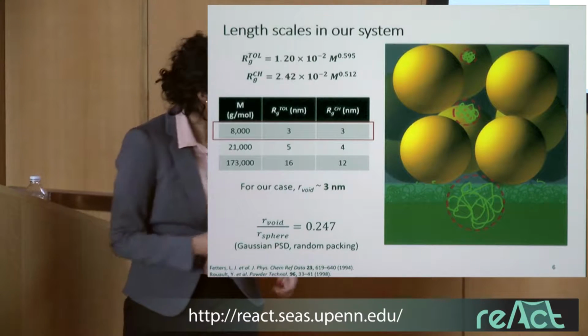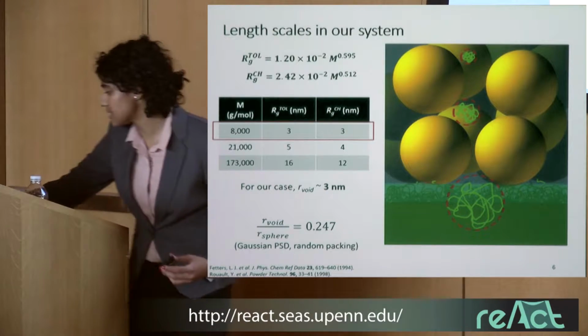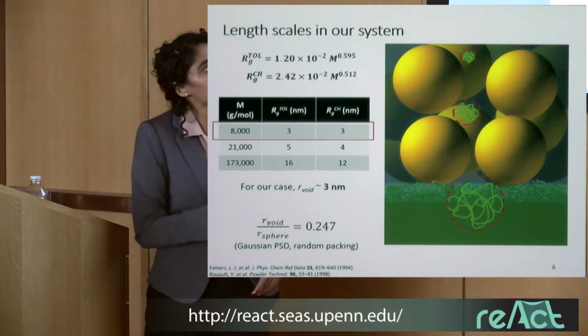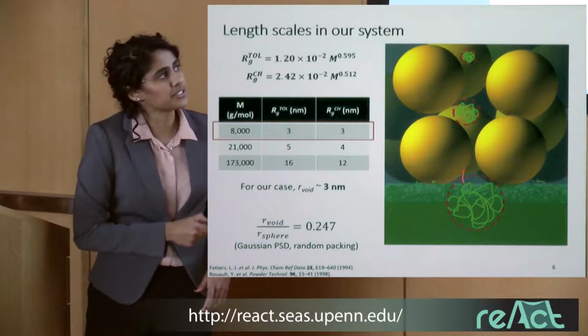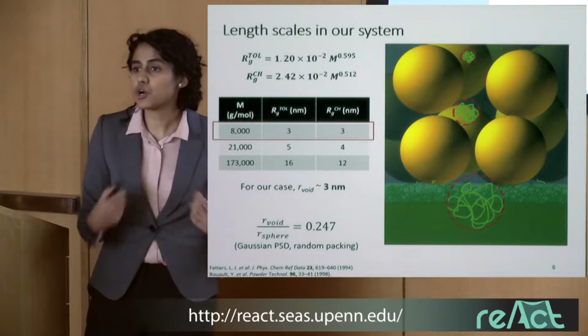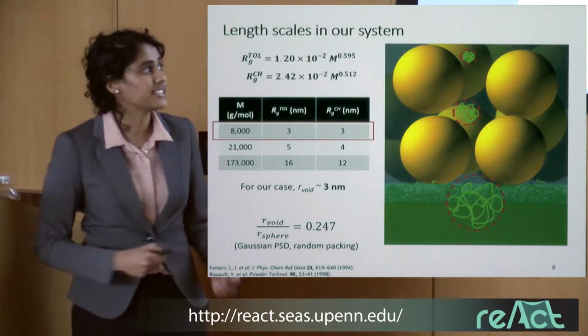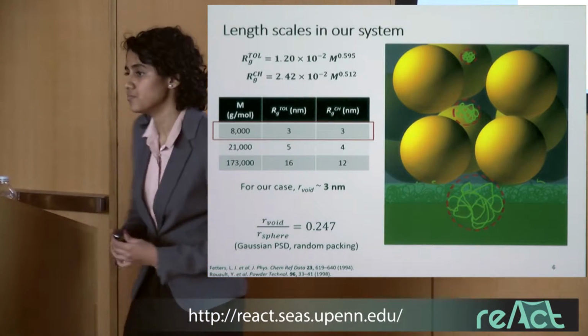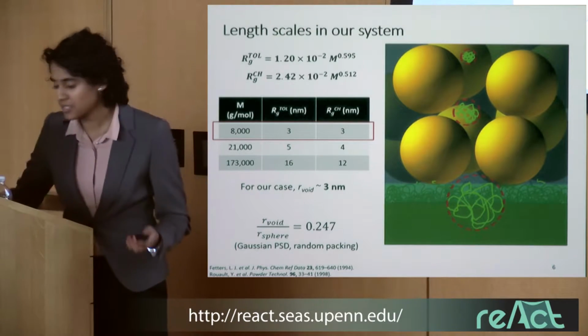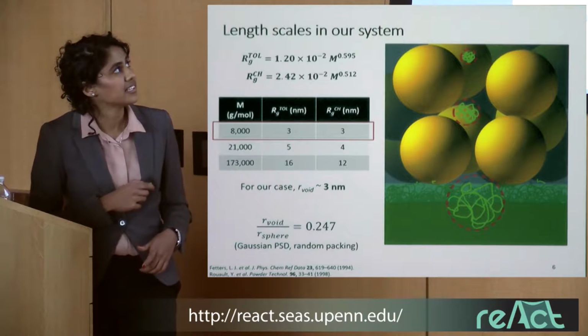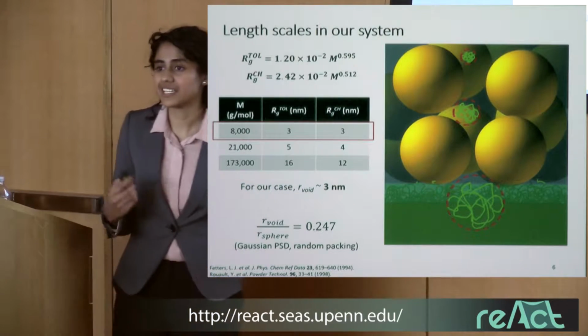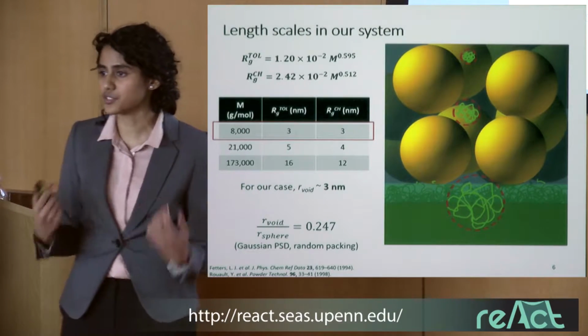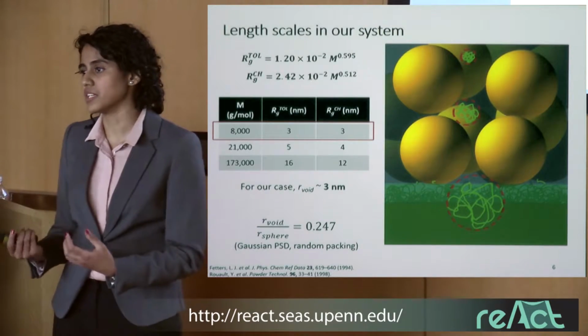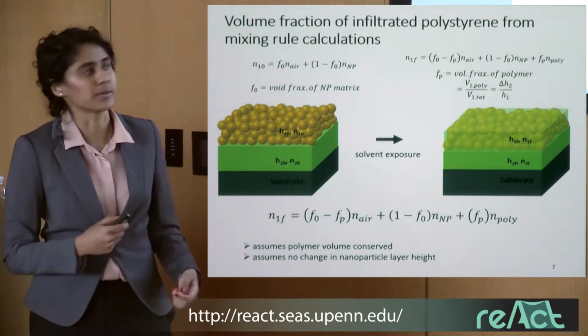So we need quite a high driving force in order to drive this polymer into the system, and we're hoping that mixing with the solvent, or solvation, will drive the polymer to infiltrate. And I'm going to focus today on the 8K, so this low molecular weight system, but I can tell you that I've observed infiltration with all of these molecular weights, even for the higher molecular weight.